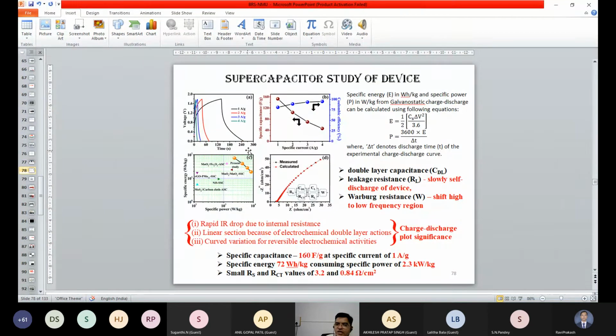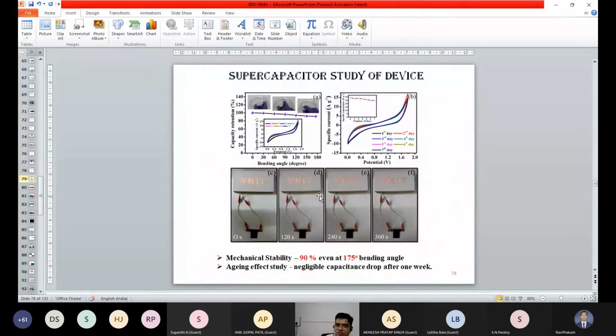Not only this, we have calculated the specific capacitance, energy density, power density, and we observe a very high value of the specific energy, that is 72 watt-hour per kg, at the specific power of 2.3 kilowatt per kg, because of the very low resistance that we observe across the interface between the gel electrolyte and the active electrode. We have calculated this through impedance analysis called EIS, electrochemical impedance, by using a two electrode system.